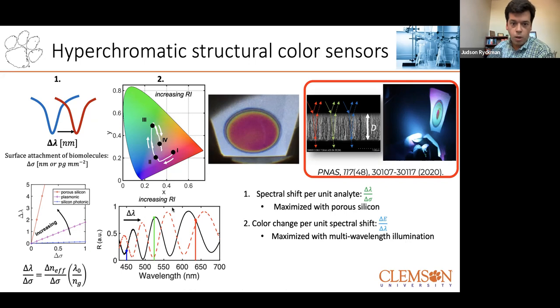In this case, this is not small molecules. This is just the infiltration and surface absorption of water vapor into the pores. So you see, if we have the sample in air, we have the black spectrum, a standard Fabry-Perot interference pattern based on the R1 and the R2 of the top and bottom interface. And as you infiltrate, say, water and begin to fill the pores, the refractive index goes up and the wavelength begins to shift. In this case, as we infiltrate water vapor, you see a very strong color response.